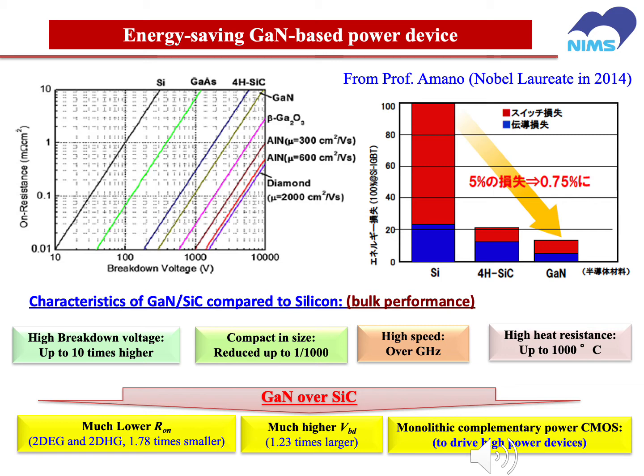This expression is from Professor Amano, who won the Nobel Prize in 2014: by using the gallium nitride power device, the switching loss can be greatly reduced compared to silicon or silicon carbide. Gallium nitride has up to 10 times higher breakdown voltage than silicon, a very small size, around 1000 times smaller, and very high speed because they can achieve the two-dimensional electron gas at the heterojunction, and a very high heat resistance. So it is very promising to replace the current silicon or silicon carbide for the power